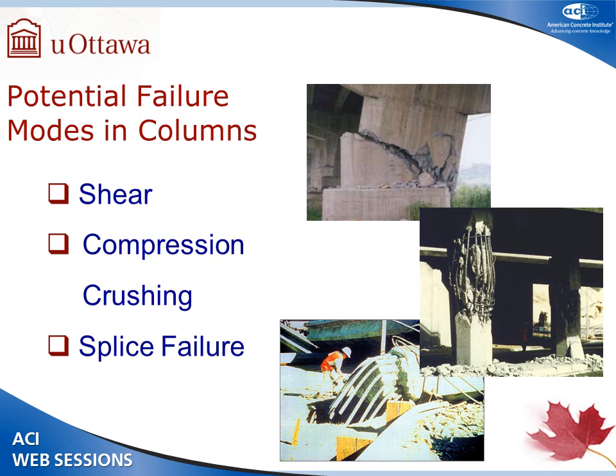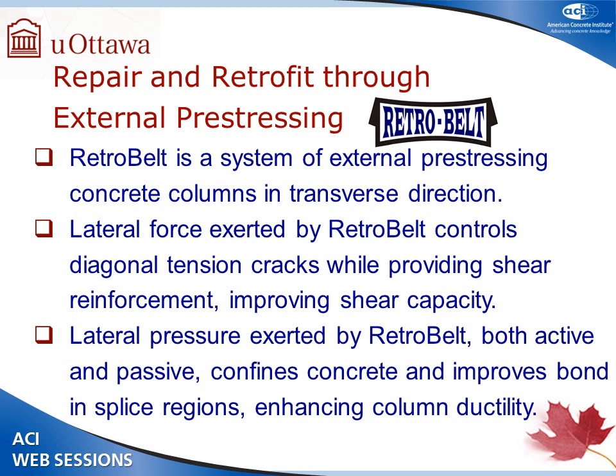In terms of bridge columns, we face these three well-known seismic deficiencies: one being shear, the other being lack of confinement under compression combined with flexural compression, and then lack of proper splicing in potential plastic hinge regions. To overcome these problems, we are undertaking an unusual application of prestressing, rather than in the longitudinal direction, applying it in the transverse direction. The uniqueness of the technique is to apply active pressure in addition to passive pressure.